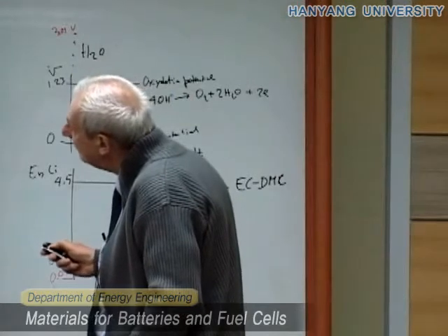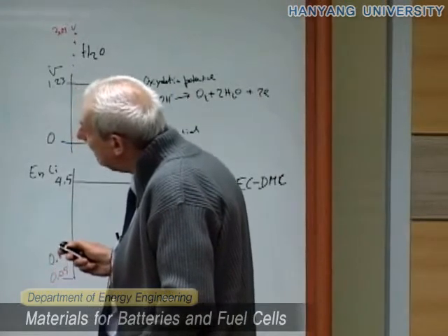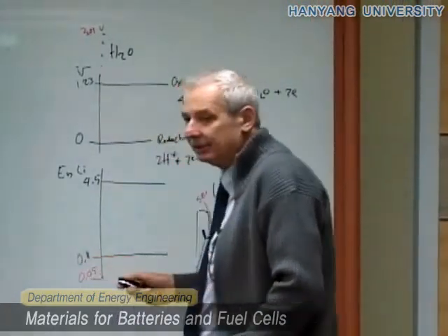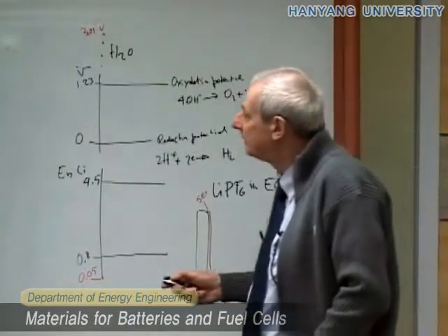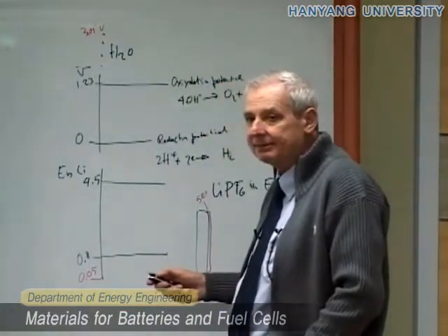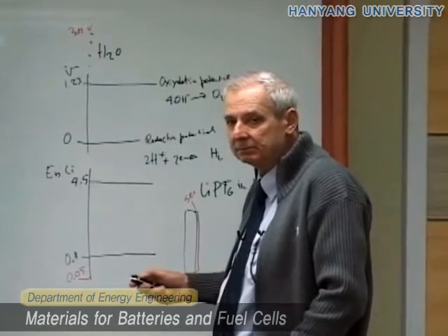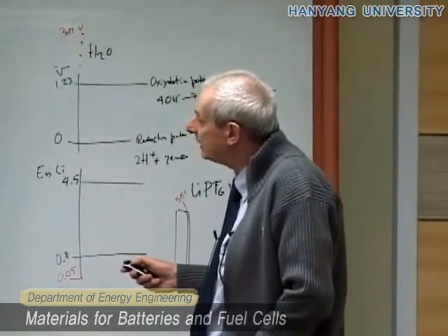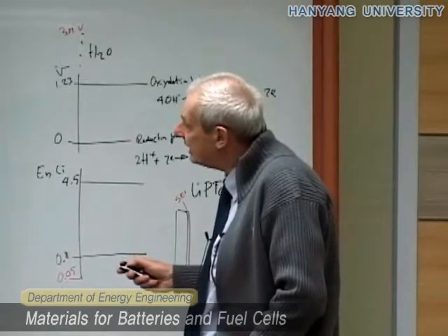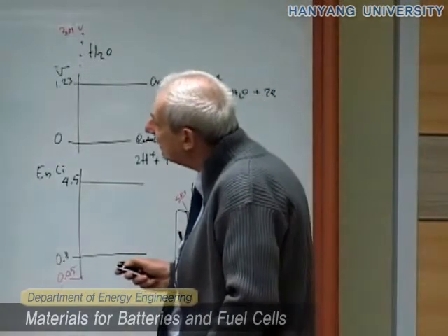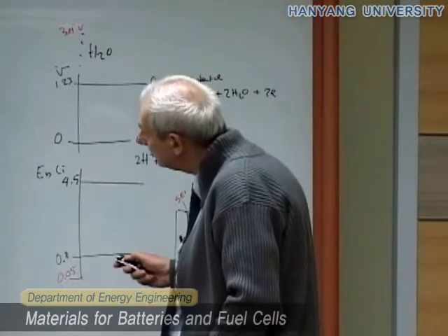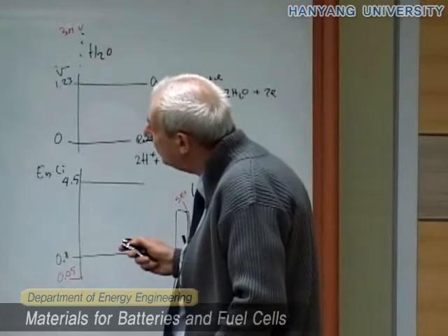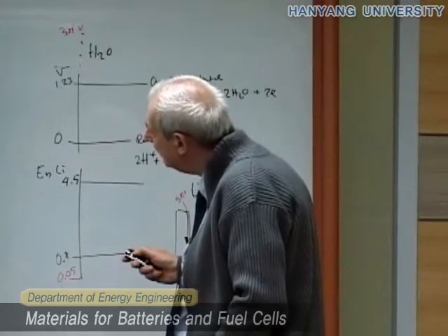You see that by many studies that I don't report here, mostly by SEM visualization, macroscopic visualization, and also by IR spectroscopic tests, the nature of this SEI is now being clarified. Actually, it seems that this SEI is formed by an organic part and an inorganic part.